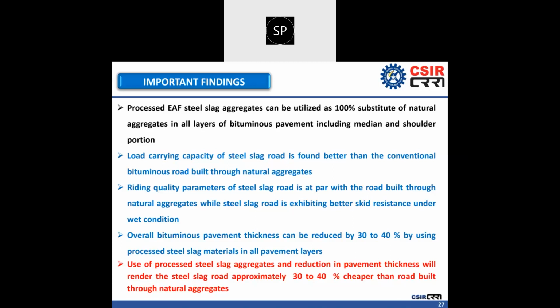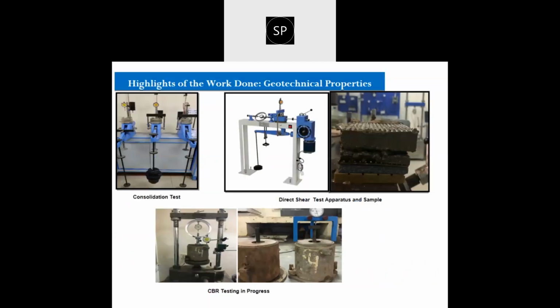So use of processed steel slag aggregate, which at the primary instance is cheaper than the natural aggregate, and the reduction in pavement thickness, we can construct an asphalt road at 30 to 40% cheaper than the road built through natural aggregate. So in terms of the economics, this material will offer you a cost-effective option to construct a steel slag road at a 30 to 40% lower cost than the natural aggregate section. So now we will take a 5 minute break and then I will discuss the second part.